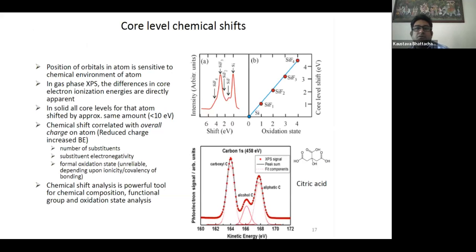Similarly, now the core level shifts. The position of the orbitals in the atom is sensitive to the particular chemical environment of that atom. So we are taking the gas phase. If I have, for example, a different amount of fluorine around the silicon, like silicon fluoride, SiF2, SiF3, SiF4, the oxidation state of the silicon changes and also the amount of fluorine changes.